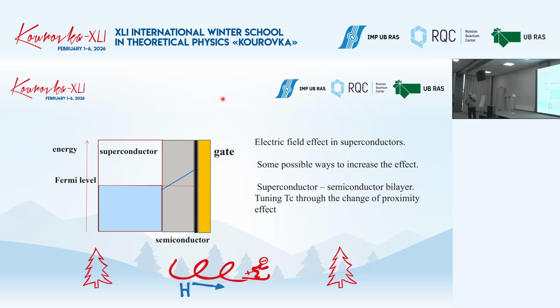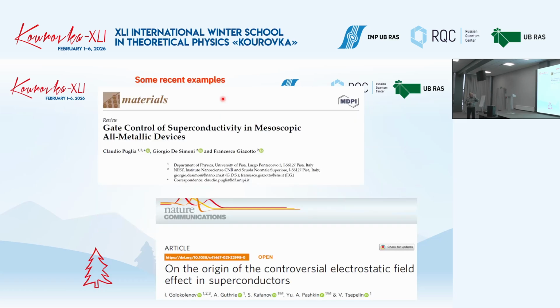So we use the semiconductor as an agent, which helps us to affect superconductivity. Okay, so is it possible? It's much better than the previous slide, but nevertheless, it's not as good as it should be. Still, this game continues, and even recently we can find a lot of experimental papers devoted to the effect of electric field. In particular, in this slide, I cite some works by the group of Giazotto, who tried to observe experimentally the influence of electric field not only on critical temperature but also on the superconducting critical current.